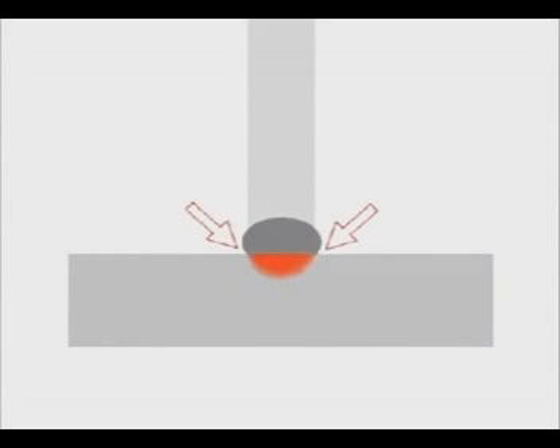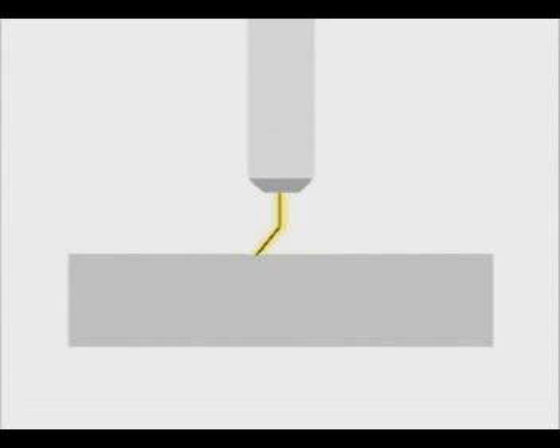If the tip of the rod is jammed right down on the metal, the arc doesn't have time to heat up the base metal. The weld bead kind of squirts out the back, not tying in well on the sides. If the arc gap is too long, the arc itself can jump around. Penetration will vary and you lose control of how the filler metal is deposited. Maintaining a constant arc gap is the first step to controlling the molten puddle and producing a uniform weld bead with consistent penetration. The better you learn to control that arc gap, the better you'll be able to weld.